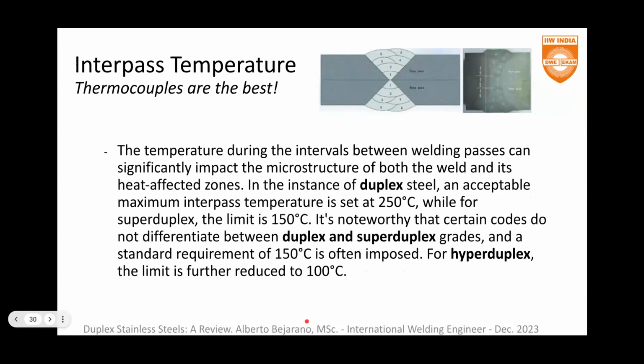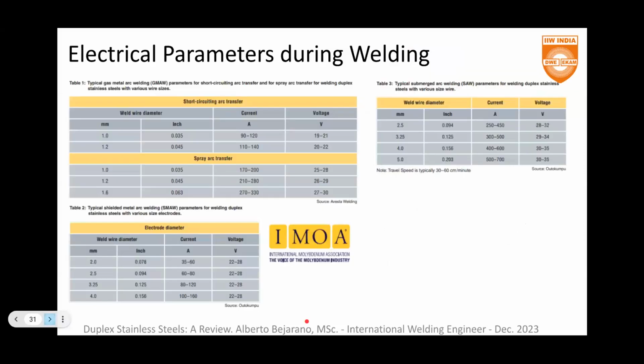becomes this T sub zero. T sub zero is related with the cooling rate. The cooling rate is related with the amount of austenite, and as you remember, this relation between all the variables and the process is true. We have to consider everything, try to do our best in order to control our welding process, and that means to control base metal, the filler metal, the shielding gas, the procedure, the qualification of the welders, the way in which we measure ferrite, etc. Okay. Great. Amazing.